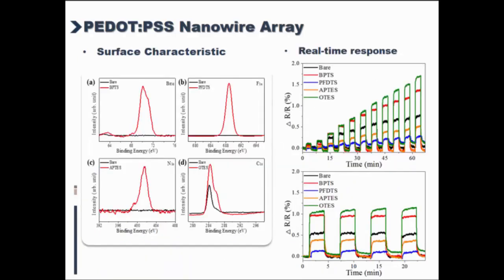And from the XPS result, we can see that the gas sensitivity materials have been successfully fabricated on the PEDOT:PSS nanowires. And with the gas analyzer in the analytical chamber, the analyte absorbed into the polymer nanowires, and the resistance increased. By flushing with nitrogen gas, the analyte dissolved immediately, and the sensor response recovered to its initial steady state.